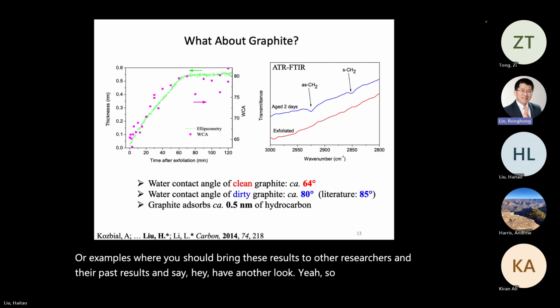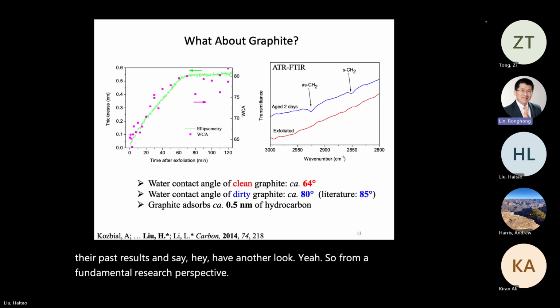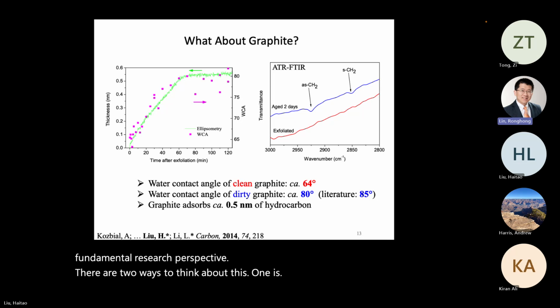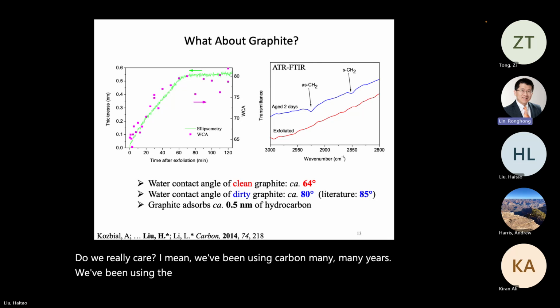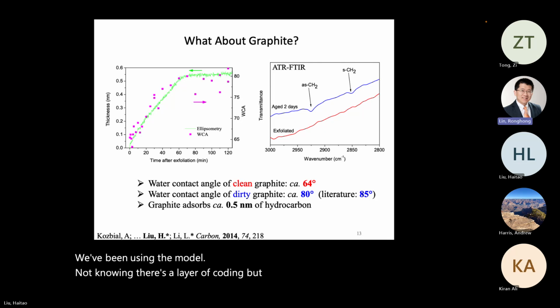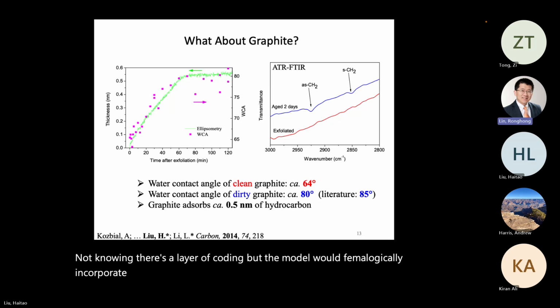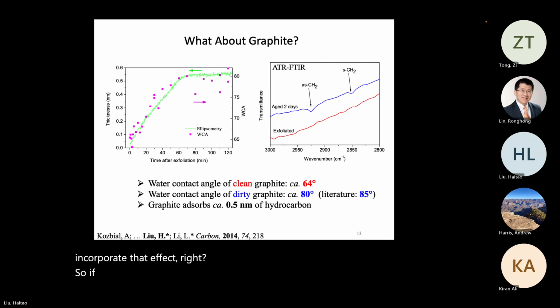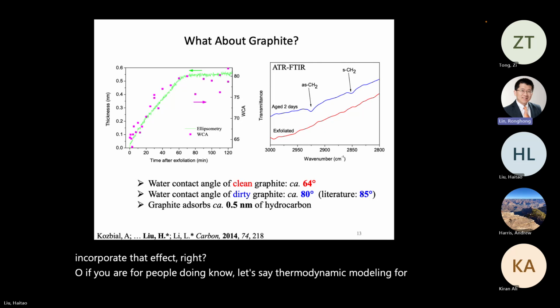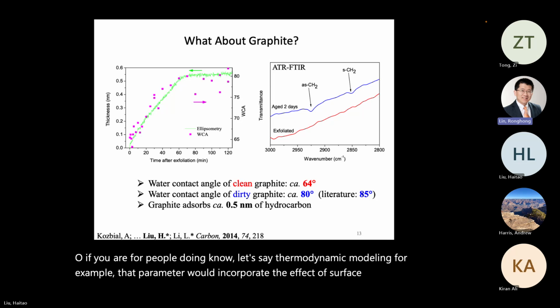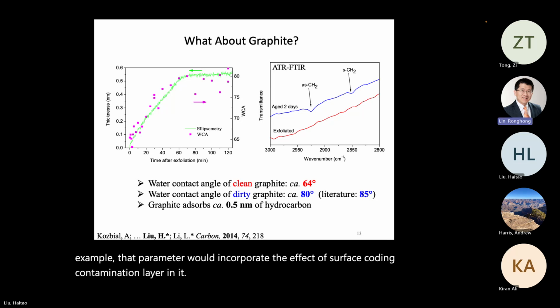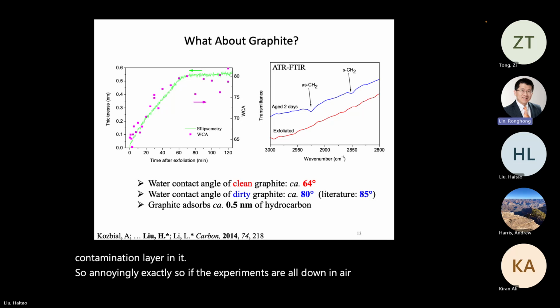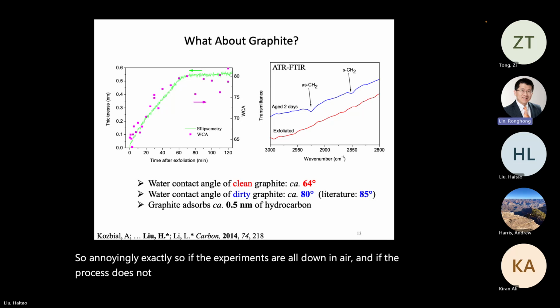Yeah, so from a fundamental research perspective, there are two ways to think about this. One is, do we really care? I mean, we've been using carbon for many years. We've been using the model, not knowing there's a layer of coating, but the model would phenomenologically incorporate that effect, right? So for people doing, let's say, thermodynamic modeling, that parameter would incorporate the effect of the surface coating, the contamination layer, unknowingly. Exactly. So if the experiments are all done in air, and if the process does not involve the intrinsic presence of the surface coating, maybe it doesn't matter at all. Now, in other cases, maybe it does.